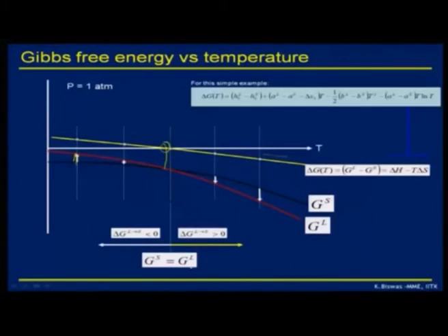So that is why from G I have moved into delta G, because delta G is easy to handle, and you know how delta G is given? Delta G is given by this equation. You can see here the zeros are your reference terms, minus A_L, A_S, A_L is A for liquid, A_S is A for solid, minus delta S0 times temperature, minus B terms, temperature square divided by 2, and then a T log T term comes.